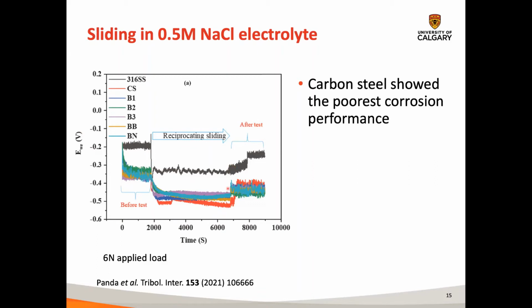And then we stop the experiment here, and we see that the working electrode potential goes to a less negative value. And so we do this because we want to wait for basically an oxide to form. So you see particularly this green line arcs down to a constant value here, and we wait for that to happen before we start the experiment. And what we see here is that the less negative the working electrode potential is, the less likely this material is to corrode. So we see here that the stainless steel performs the best, and the carbon steel performs the worst, okay? Which is obvious to most corrosion scientists here.